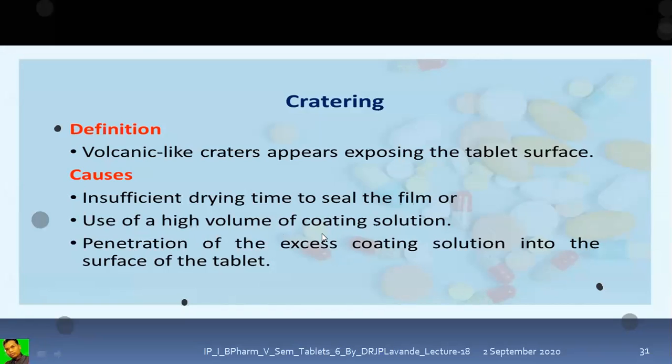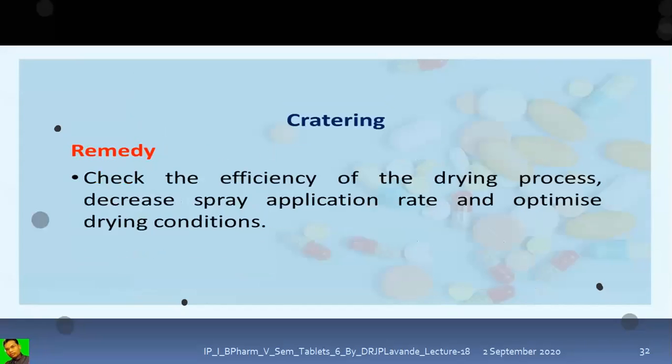Instead of spraying, if we pour the coating solution, it will also lead to the cratering defect. Penetration of the excess coating solution into the surface of the tablet: if the solution enters the tablet surface through its pores, then we are going to find these craters. The remedy is to check the efficiency of the drying process.